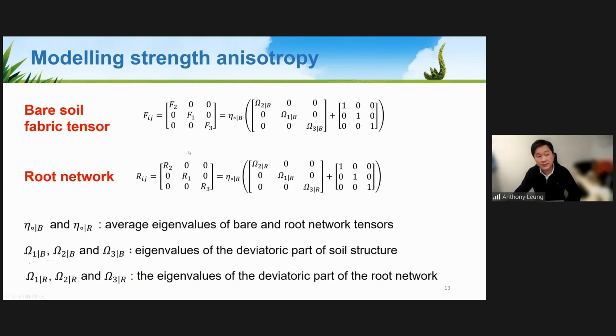Then we propose a new fiber anisotropy tensor for the root network to describe the root distribution. So as you can see, the mathematical form is similar, actually the same as the bare soil fabric tensor, but using different parameters to capture the anisotropy or the microstructure because of the root network development. Okay, so we do have a lot of parameters, the eigenvalues, the mean values of the eigenvalues of the deviatoric part of this matrix. So those are the parameters that need to be calibrated for the modeling.